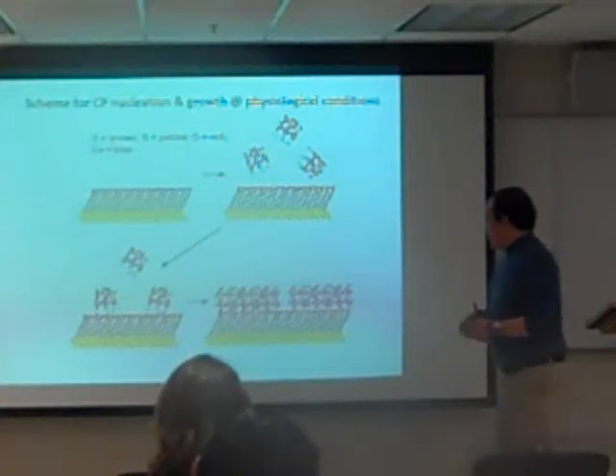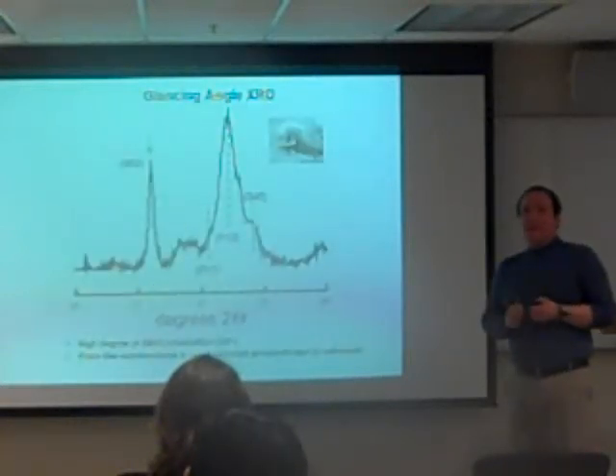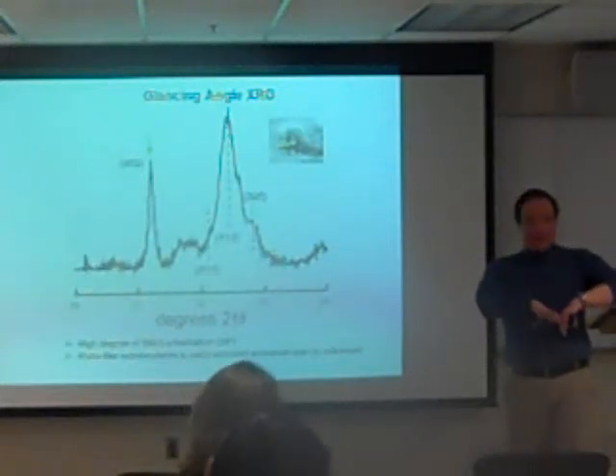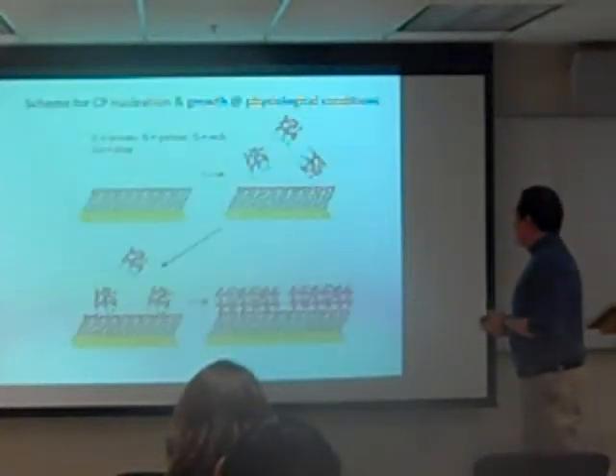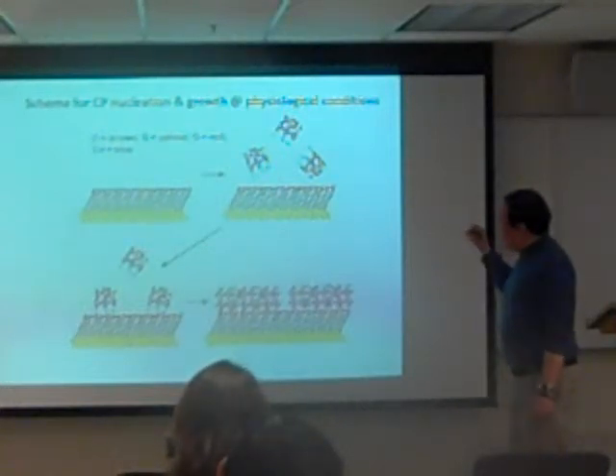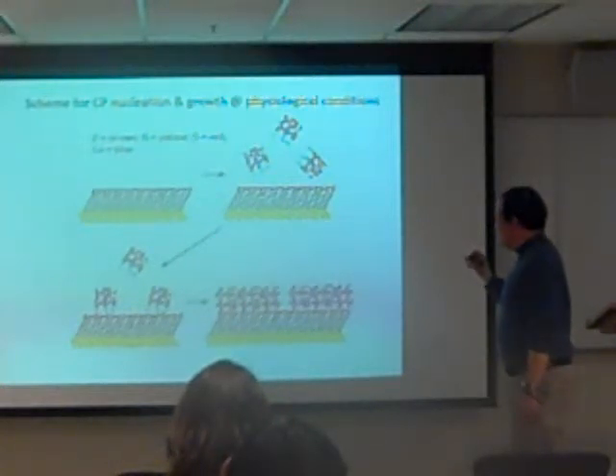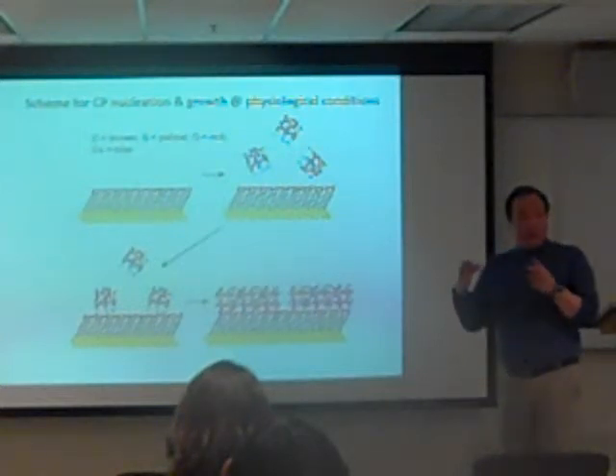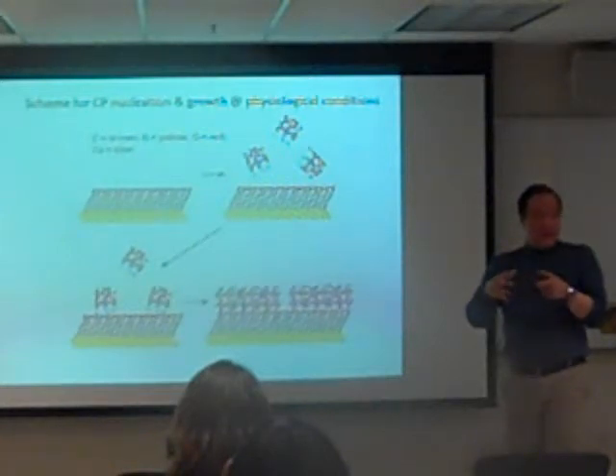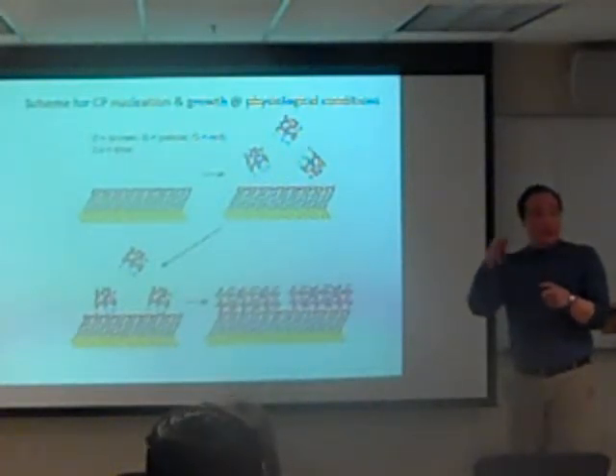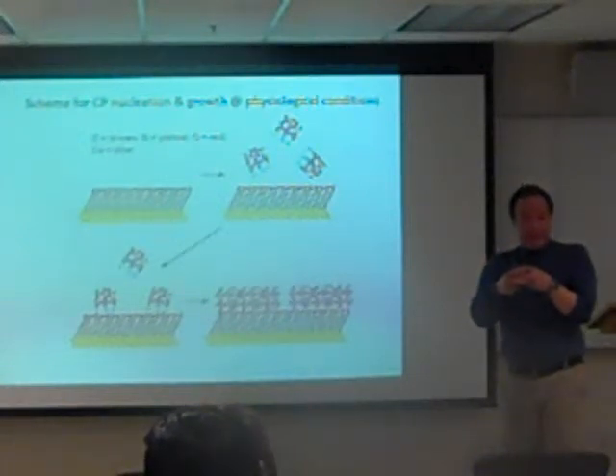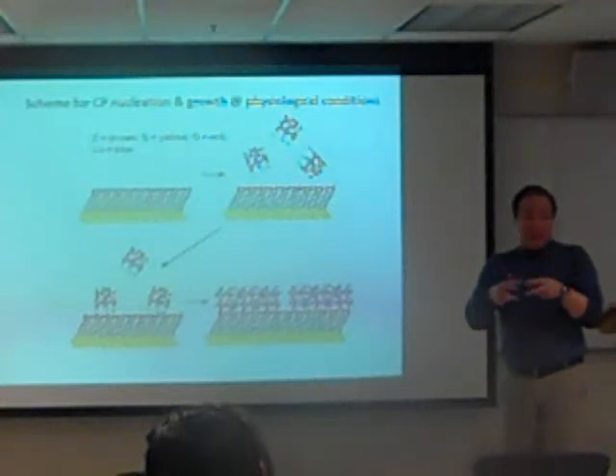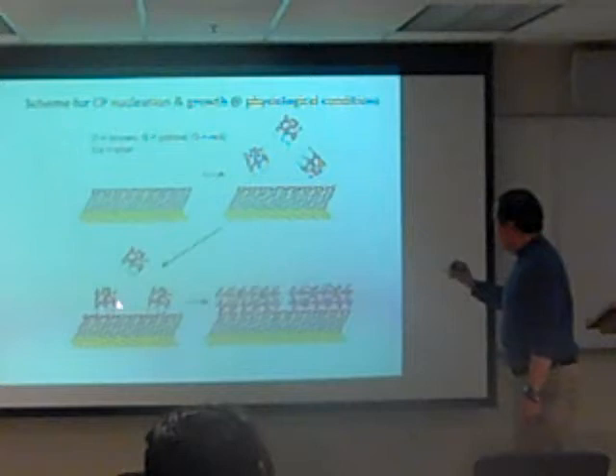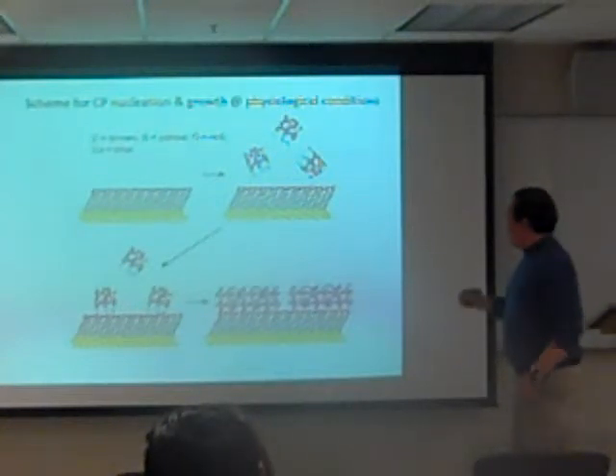Now, to explain what's happening here, it looks like at the early stages of growth you have some adsorption of calcium and phosphate, but then something else needs to happen. It would seem that this model is consistent with what we think is happening: a nucleation occurs in the solution itself. It's basically a critical cluster nucleation mechanism. Nucleation has to occur in solution, where it needs to reach a critical point, and afterwards it deposits onto the surface. That's where we see the rapid growth of the calcium phosphate.